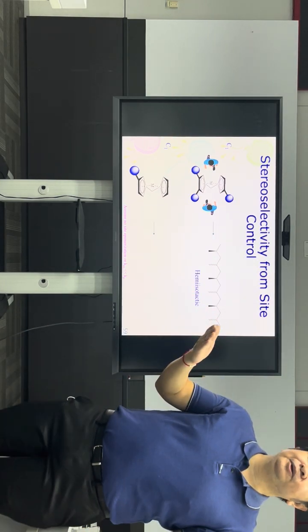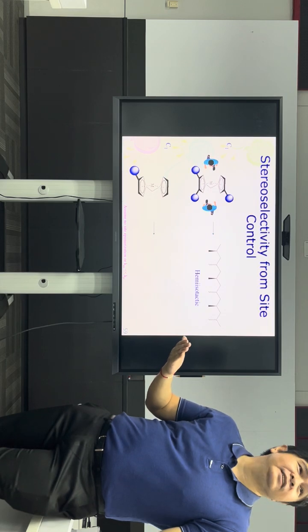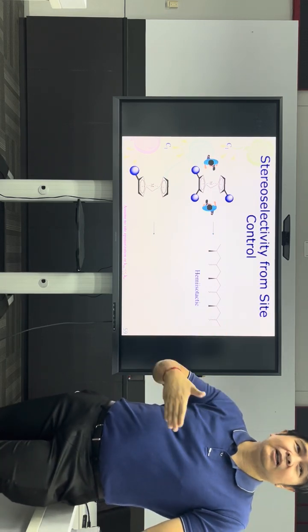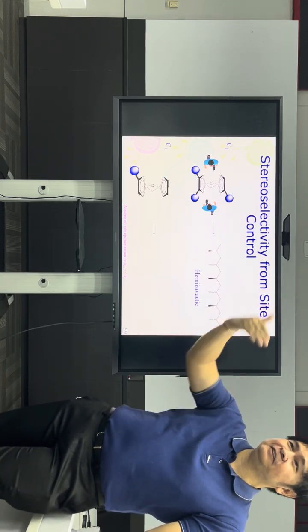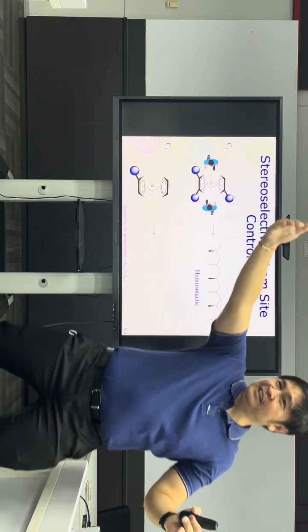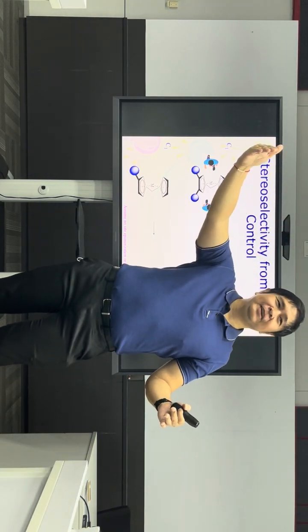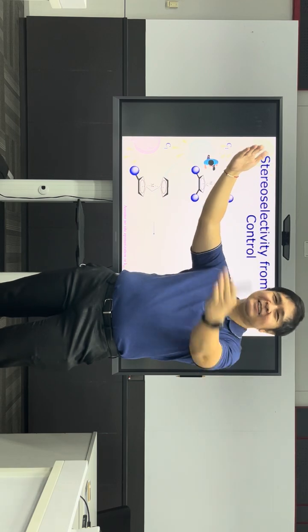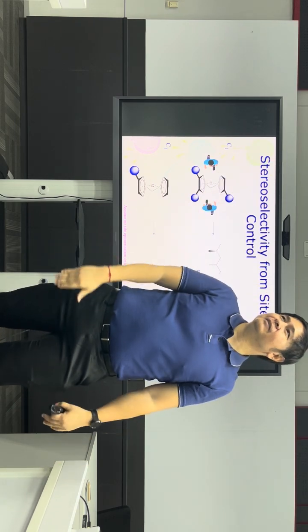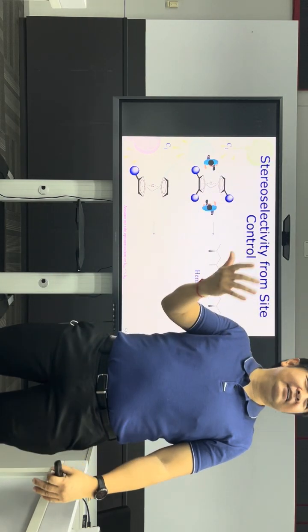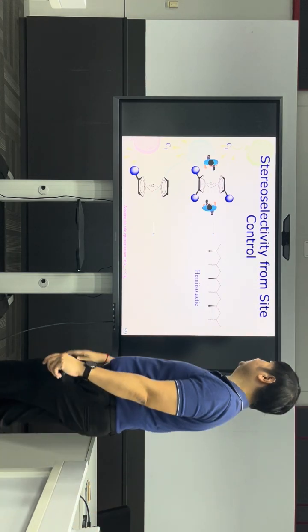But let's say you do polymerization at 1 atm, for example, with a small amount of ethylene. Ethylene may not feed in time. Before the next monomer can come in, the ethylene doesn't come yet, so this thing just scrambles and plays around. So there are many factors that actually control the site epimerization.